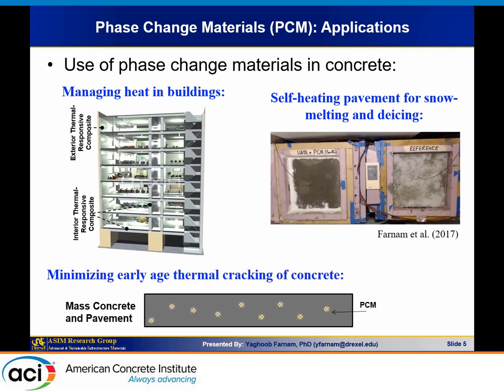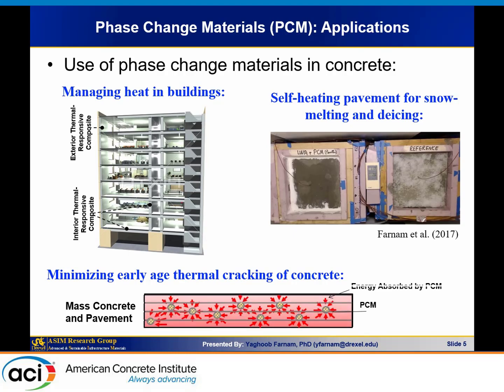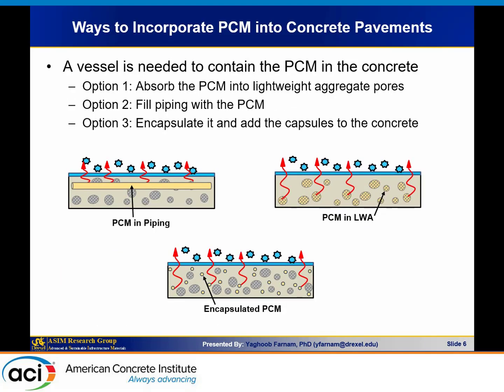The other idea is, again, the mass concrete or pavements, where you have some types of internal heat generation through hydration, or it might be some pavement that is exposed to very hot temperature, like in Arizona. And the idea is that as you have this heat released through the cement hydration, this PCM serves as a thermal reservoir, and it could actually suck the thermal energy from the surrounding environment, so you don't get that much thermal cracking. So the question is how we want to incorporate phase change materials inside concrete, and different methods will have different types of performance.